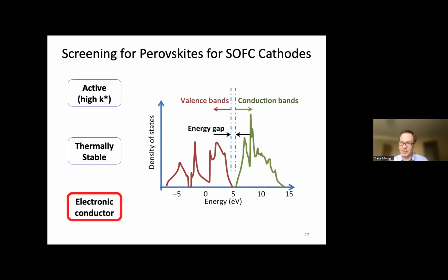Then, how do I decide if it's an electrical conductor? There are a few tricks for this, but the major approximation is I make sure it doesn't have a big band gap. I can calculate the band gap when I do an electronic structure calculation. It comes out for free. And if it's large, or even reasonably large, half an eV even, it's probably not going to be a good metal even at high temperature. And then we would discard it from our list of candidate materials.